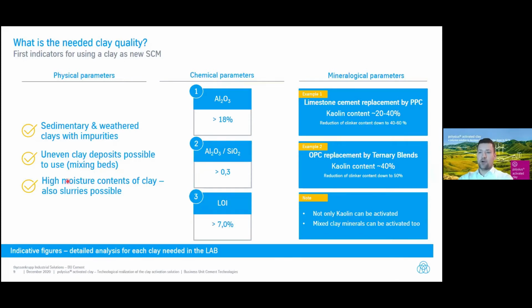And the last point here from the physical parameters is the moisture content. So we are able to handle up to 35 or 40% of moisture with our equipment. For sure, this will have an impact on the heat consumption at the end. So this must be in line with the business case. But typically, we are more talking about moisture levels between 10, 15 to 25%. This is typical for clays.